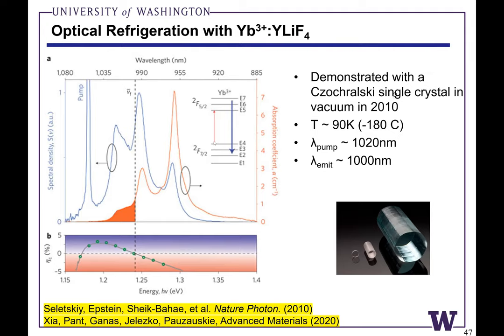So you can think of this sort of like running a laser in reverse. Normally, if you run a laser, you'll pump from a ground state to an excited state. You'll dump phonons into the crystal that heats up the crystal, and then you have lasing that is useful for any number of laser heated diamond anvil cell applications, for instance. But in this process, it's the exact opposite. You start with a laser coming in, you create the excited state, and then the excited state absorbs phonons from the crystal lattice, and then spontaneous luminescence is emitted.